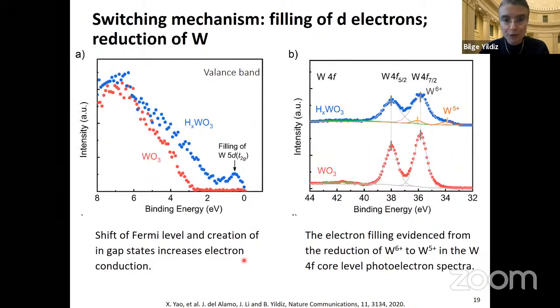And in order to test that, we have performed X-ray photoelectron spectroscopy, both in the valence band and in the tungsten 4f region. And in the valence band, what we can see here is, after protonation, formation of this additional state, which corresponds to the filling of the tungsten 5d t2g state, as I introduced qualitatively in the previous slide.